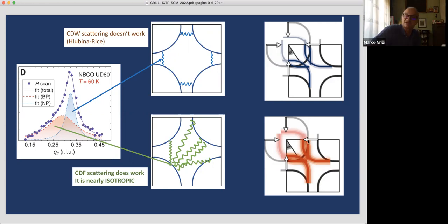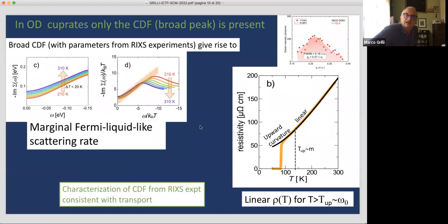And when you do the same exercise on the Fermi surface with this pinkish mediator, you find that essentially the whole Fermi surface is hot. So they work as a good isotropic scatterer. And this interaction in the overdoped region, where no charge density waves are present, only charge density fluctuations are there, you can calculate the self-energy in perturbation theory. So the effective coupling that you need to fit, for instance, the transport is rather small. The dimensionless coupling is around 0.4, 0.5. So perturbation theory works well.